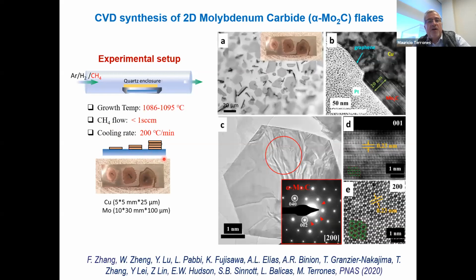And then you end up having these beautiful, very thin crystals of moly carbide. So these are hexagonal or triangular crystals of moly carbide. You have this sort of striping, which are stacking faults, but here you can see the thickness of these crystals, let's say it's like 20 nanometers, very thin. Again, this is bulk, and you have beautiful patterns. So this alpha moly carbide is a superconductor, but you can make these beautiful crystals.